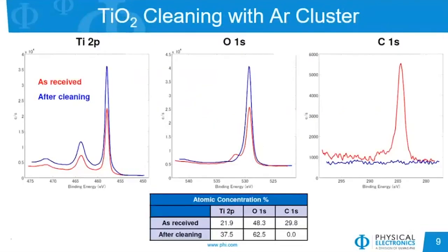However, using something like a cluster source, we do see that we can effectively clean the titanium surface without seeing damage. If you look at the Ti2P peak, we see a very small change in the after clean peak, and we can also see that the carbon has been effectively removed and our oxygen peak is more representative of a titanium oxide.